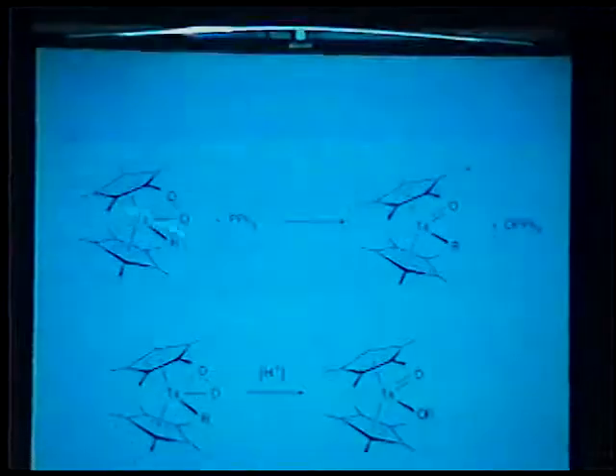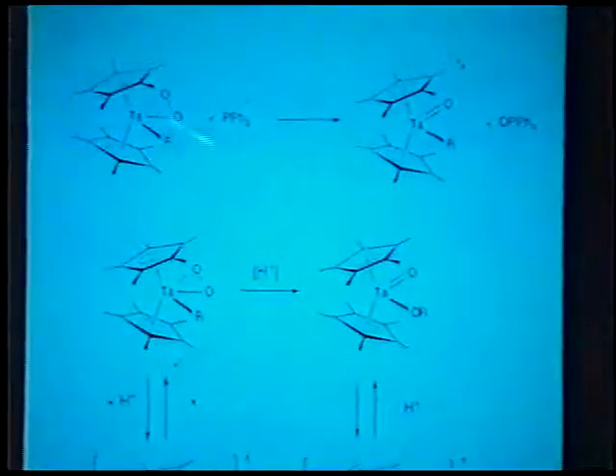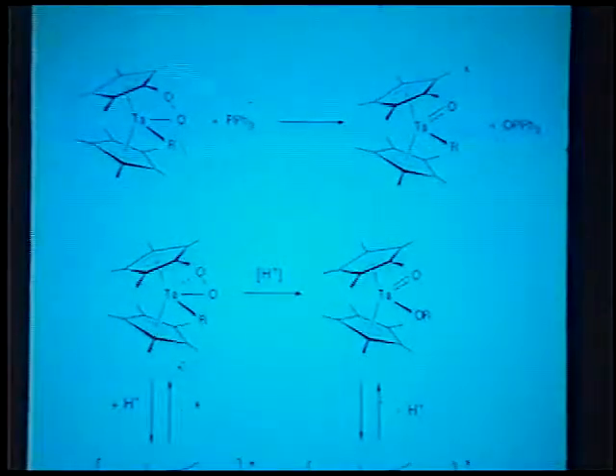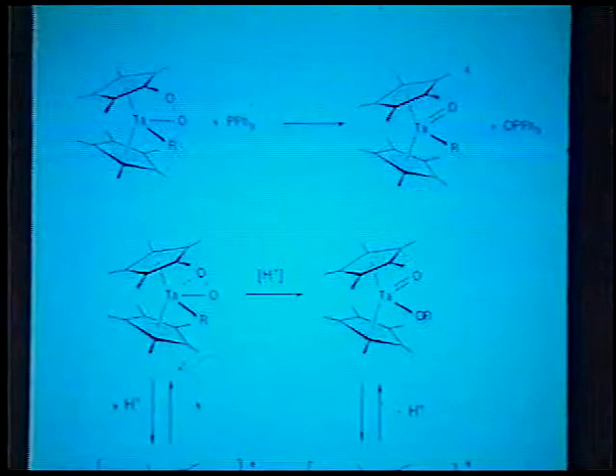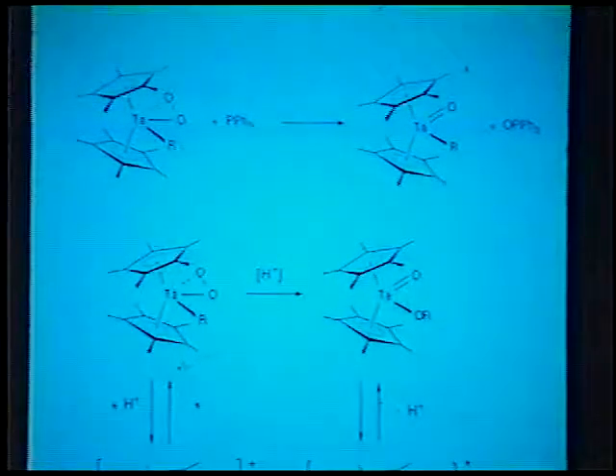transformation. With this peroxide alkyl that I described earlier, we find the expected chemistry in terms of oxidation of triphenylphosphine to triphenylphosphine oxide. We found no oxidation of styrene, however. But we did find when we added styrene, we got a very clean transformation that did not consume styrene.